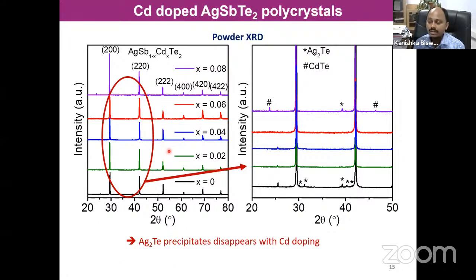For example, we did powder X-ray diffraction, which is the fingerprint experiment, to check whether any order-disorder changes are happening in the sample. X equal to 0 is the pristine sample, AgSbTe2. AgSbTe2 always forms slightly non-stoichiometric in the phase diagram of Ag2Te and Sb2Te3, so it always has an Ag2Te-type impurity, which destroys the thermoelectric property of AgSbTe2. But as soon as I dope cadmium, 2 mole percent to 4 to 6 mole percent, the Ag2Te peaks slowly go away. You don't see them, so something new is chemically happening in this sample.